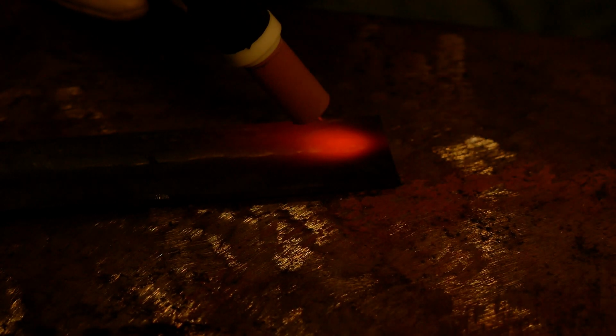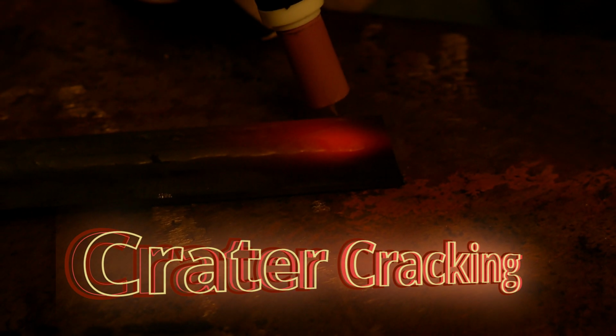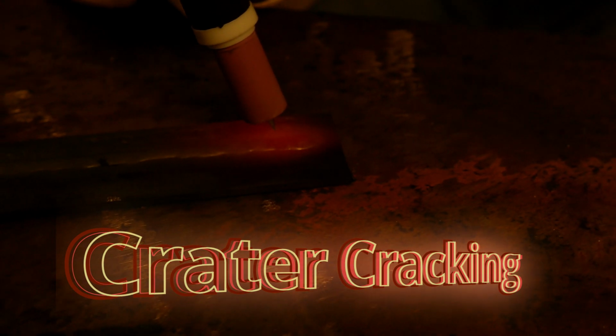Don't be intimidated if something happens. Simply stop, fix your filler material or your tungsten, and tie back into the weld again. When you get to the end of your weld, add a couple extra drops of filler material as you slowly extinguish your arc. This will help to fill in and eliminate any crater that would happen. Crater cracking is common, so this is a good technique.